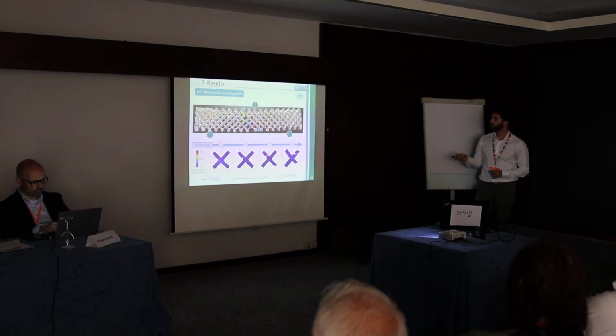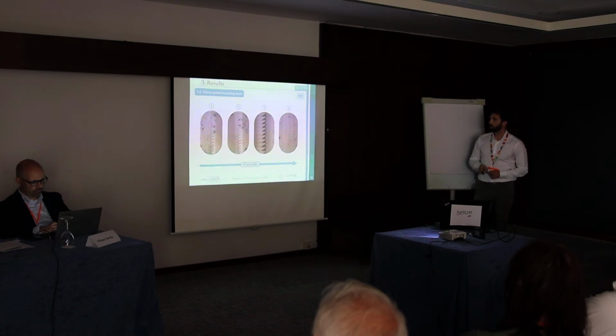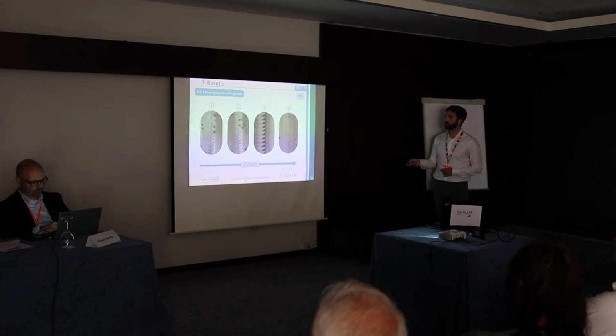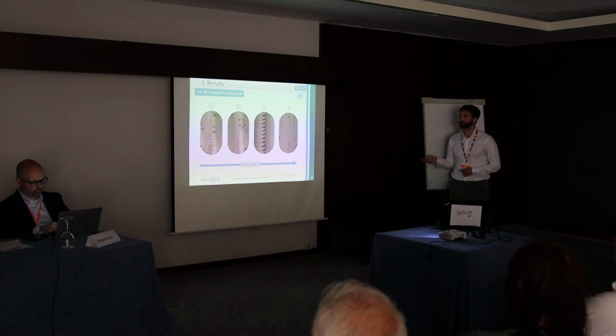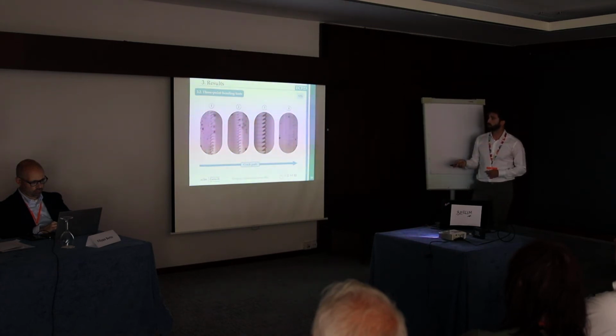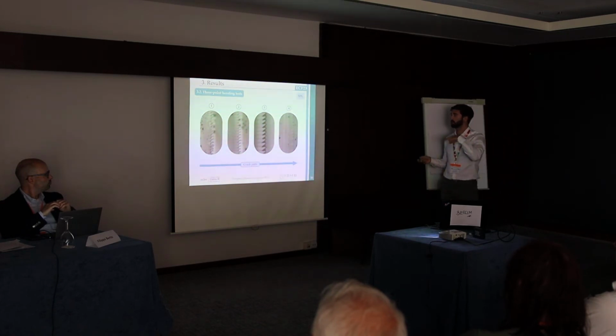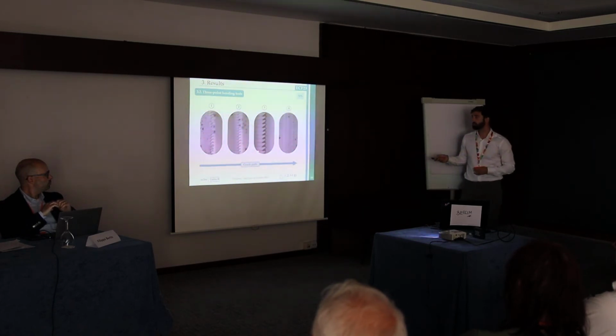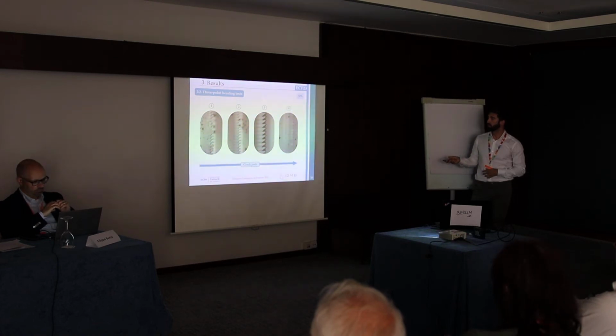And we can see this too from a microscope view. These are again the four joints of the crack path. In the first and second, we can see some plasticity. Well, this is after the fracture, but this is forming before the fracture. And then on the third joint, which is in the middle of the neutral fiber of the specimen, we can see an intact filament here, and then an abrupt fracture, because this is a rough surface. Okay, this seems like a rough surface.